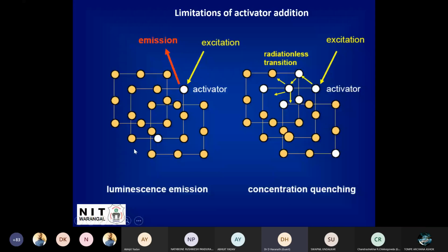Okay. And after a while, you see that the intensity is dropping down again, even though you are increasing the activator. Because when this activator is emitting visible light, it is absorbing ultraviolet and emitting visible light, and the rest of the crystal will act as a transparent plastic-type matrix. It will just allow the light to go out. That's why we are able to see it. That's why you see here also one activator will absorb ultraviolet and shine a color for which the rest of the crystal will be transparent, and the light will come out and we can see. But if you add a lot of activator in a crystal, what will happen?